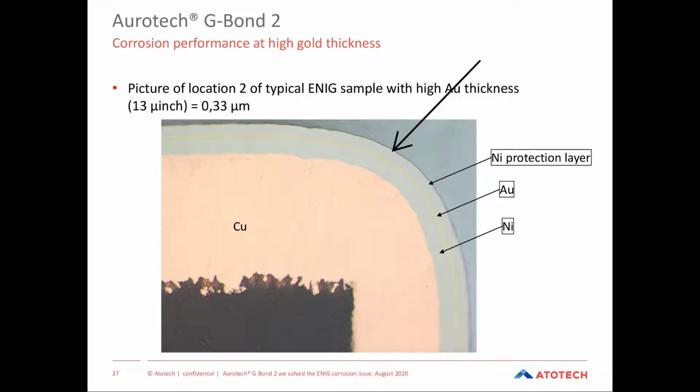So this is how we looked at it, and this is what we see. There is really no corrosion to detect, and this is the sample with a thick gold, so with 13 microinch of gold, or 0.3 micrometer.